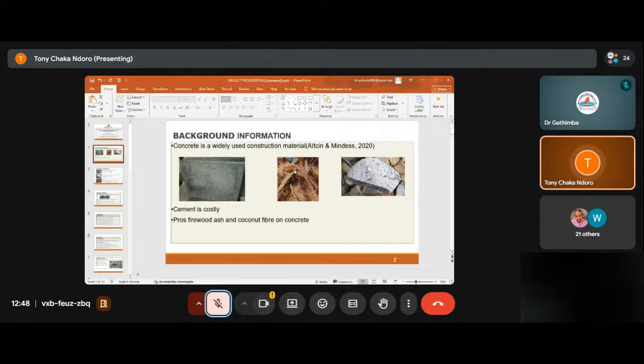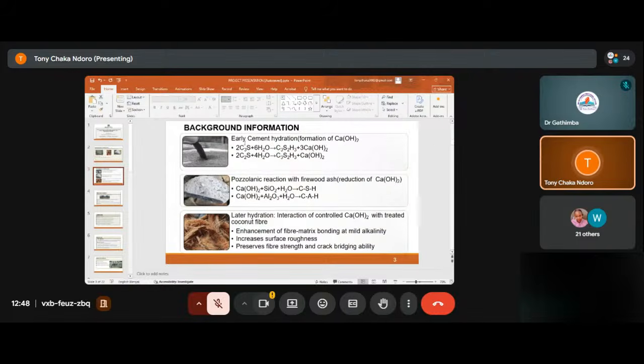There's an increase in natural and biomass waste, and cement is costly. There's an advantage of using firewood ash and coconut fiber in concrete. Background information. The early cement hydration produces the calcium silicate hydrate and excess calcium hydroxide, while the firewood ash reacts pozzolanically with the calcium hydroxide to form calcium silicate hydrate and calcium aluminate hydrate. Thereby, it will improve the strength and durability. But this reaction will not remove the calcium hydroxide completely.